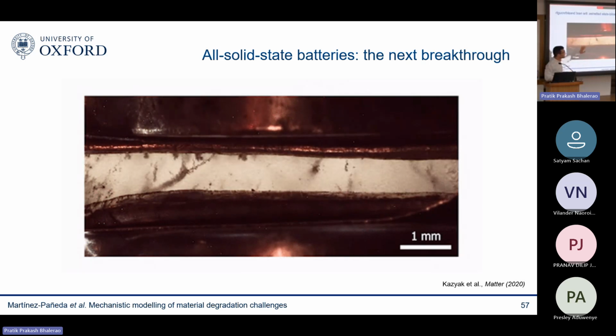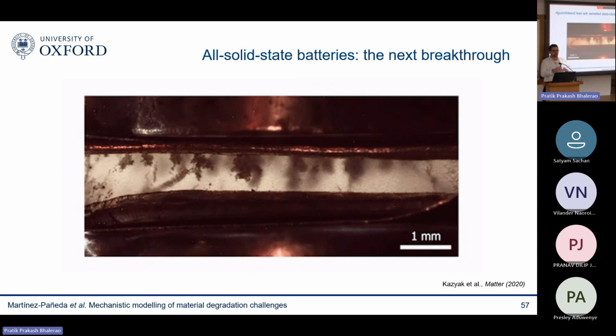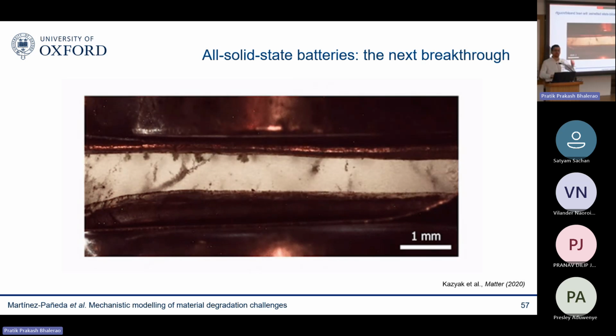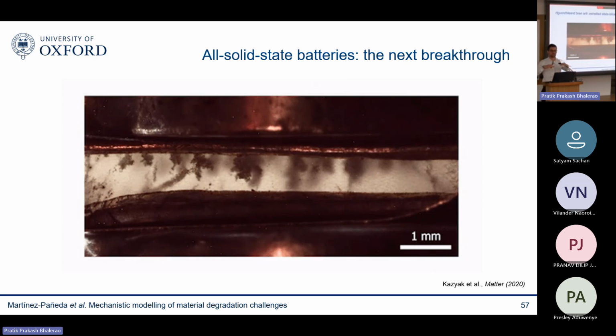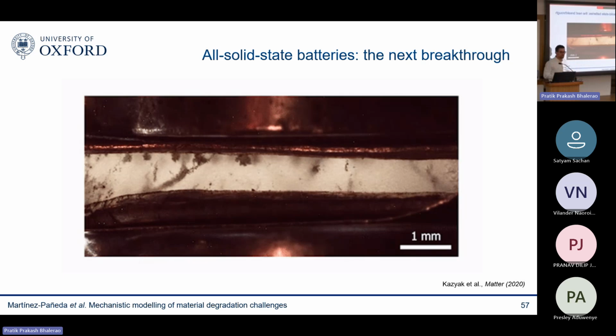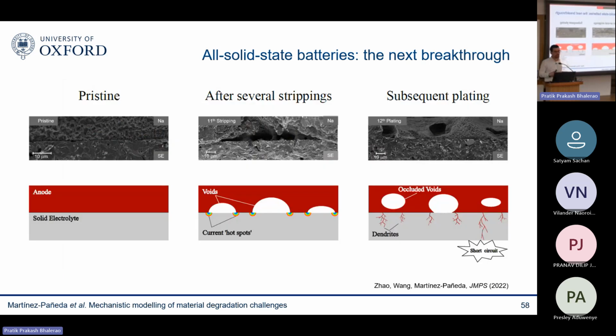And initially, the battery community was very interested in, can we stop those dendrites? So they replaced polymer electrolytes by very stiff ceramic electrolytes, thinking that maybe those stiff ceramics will block the dendrites. But that didn't happen. Dendrites continue to grow. So what we focus on in my group is, can we try to predict the nucleation of those dendrites? And for that, well, basically what happens is what you see here.